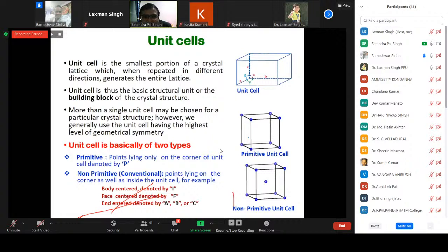Another terminology we should know is the unit cell. First we talked about X-rays, then we learned about symmetry, and now we know about the unit cell. What is a unit cell? A unit cell is like a building block which consists of 3 axes, what we call a, b, c, and these axes are known as lattice parameters. The angles between the interaxial directions are alpha, beta, gamma. So the lattice parameters are a, b, c, and alpha, beta, gamma. The unit cell is the smallest portion of the crystal lattice which, when repeated in 3 dimensions, generates the entire lattice. So the unit cell is the basic structural unit, or building block, of crystal structures.